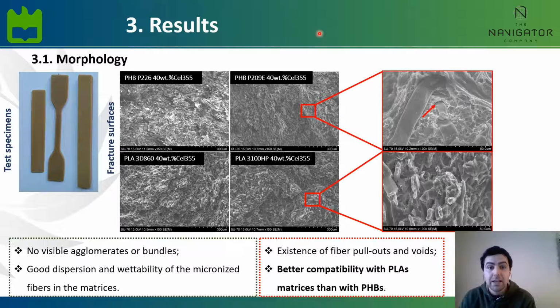On the downside, despite the good dispersion, the fracture surfaces reveal the existence of some fiber pullouts and voids, which are a sign of poor interfacial adhesion. And this closer look at the interface also allowed us to confirm superior compatibility of the fibers with PLA than with PHB. And this is going to be important to explain some of the following results.